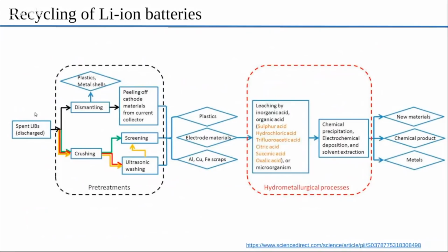You get the spent lithium-ion batteries. If it is significantly degraded, then you crush them such that all the parts come apart. Then you have the plastic shells, the metallic jacket, the cathode material, the current collectors, right? You get all that stuff, and then whatever important stuff you need, the cathode, the nickel, the cobalt, aluminum, some of those materials will be subject to pre-treatments where they're screened, and then ultrasonic washing separates them out based on the density, based on the material, based on what can be reused or not. So once the outer jacket is taken off, the inner part will be subject to the screening and washing.